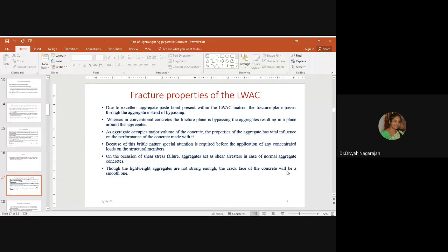Whereas in conventional concretes, the fracture plane bypasses the aggregates, resulting in a plane around the aggregates. The aggregates will not break into halves, or there will be no crushing of aggregates in the case of normal weight concrete. As aggregate occupies a major volume of the concrete, the properties of the aggregate have a vital influence on the performance of the concrete made with it. Because of its brittle nature, special attention is required before the application of any concentrated loads on the structural members. This is why fibers are required to be added in lightweight concrete.